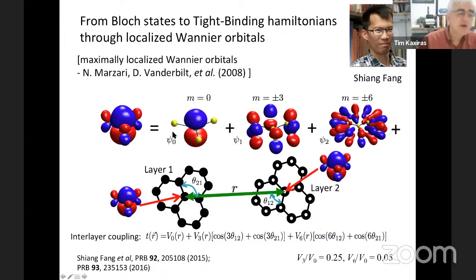The surprise when we did that was that the Wannier orbitals that you need for an accurate description are not just the PZ orbitals that we typically assume, that I showed you earlier, but they're more elaborate wave functions, single particle wave functions that look like this, and you can decompose them into the PZ orbitals with angular momentum 0 and higher angular momentum states shown here schematically. This was the work of my student Shiang Fang.